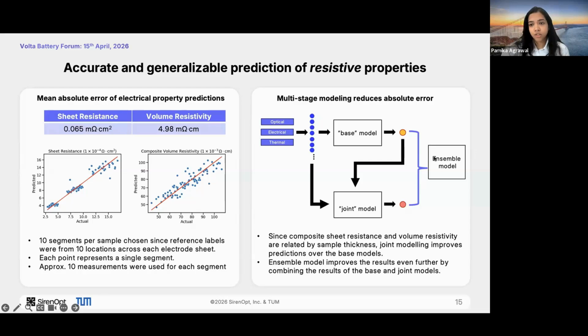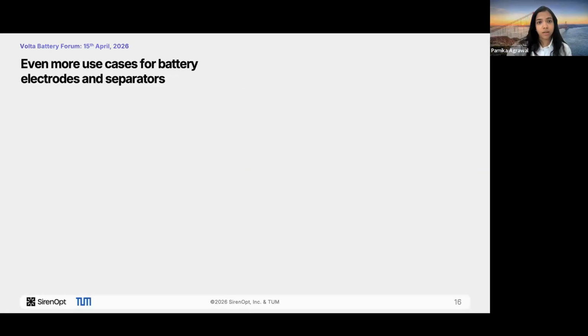A third stage is employed, which is the ensemble model, which takes an average of the predictions of the base model and the joint model, which reduced our mean absolute error even more. By leveraging physics-based relationships and employing multi-stage modeling, we can get an even better performance on certain electrode properties. That's basically the message of this slide. And so we showed 6 or 7 different properties.